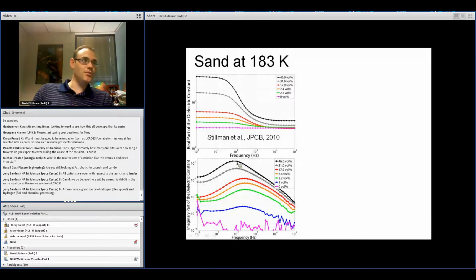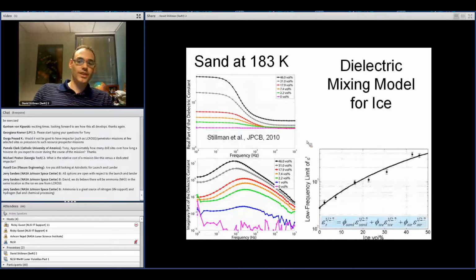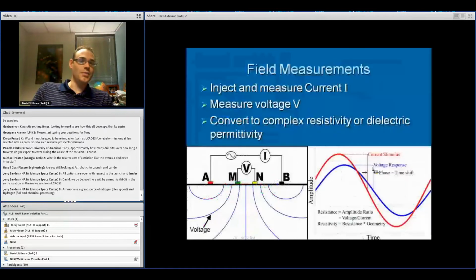It will allow us to detect ice colder, and this seems to be a pore wall effect. When the ice is very close to the pore walls, somehow we get faster relaxations. It's not exactly clear how that happens, but it always does. So we fit a dielectric mixing model to this, and you can see it fits pretty well. And this was actually theoretically predicted about 10 years ago, and the experiments show that it continues to work out. So we believe we can quantitatively map subsurface ice content. So how will we do this?